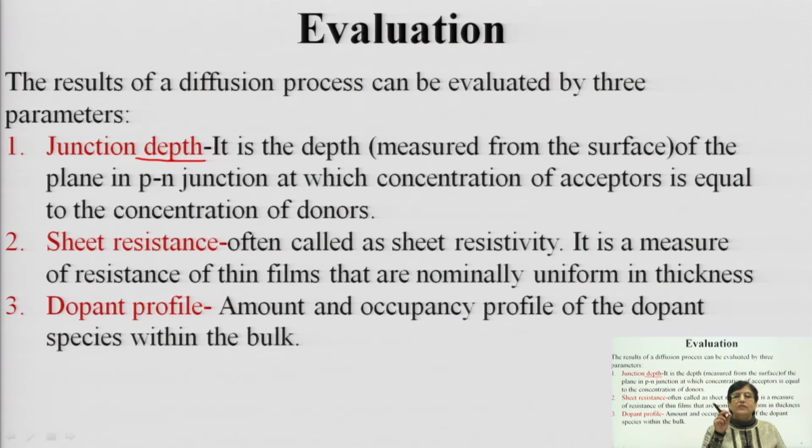Whenever we are scaling those areas, like we are taking a small portion of the entire thin film, the property will not change, and that is why, rather than direct resistivity, we carry out the sheet resistivity measurement, or measurement of sheet resistance, which will exactly give you the idea about those point contacts or small areas, especially when miniaturization and scaling of devices is happening. In the scaled structures also the sheet resistance will be the same, and therefore we are measuring that particular parameter to define the electrical characteristics.